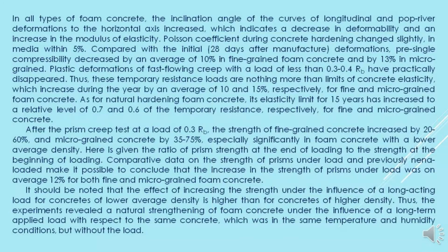diagrams. In all types of foam concrete, the inclination angle of the curves of longitudinal and transverse deformations to the horizontal axis increased, which indicates a decrease in deformability and an increase in the modulus of elasticity. Poisson coefficient during concrete hardening changed slightly, on average within 5%. Compared with the initial, 28 days after manufacture, deformations, prism compressibility decreased by an average of 10% in fine-grained foam concrete and by 13% in micro-grained.